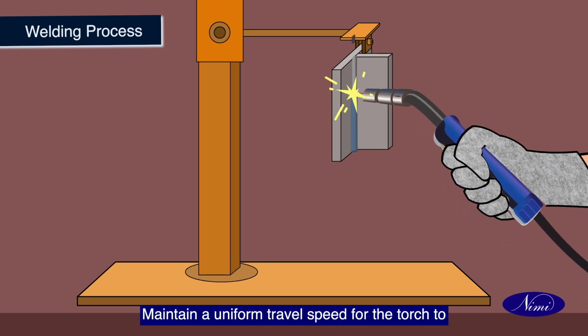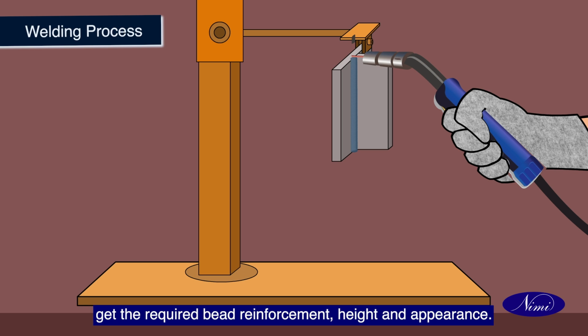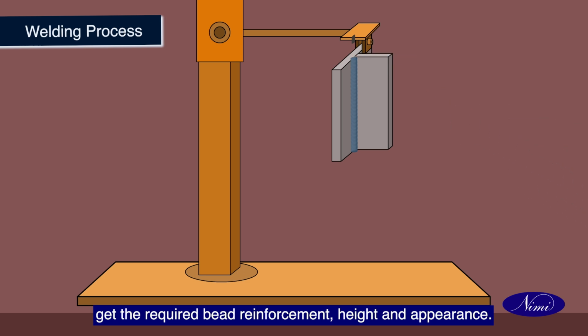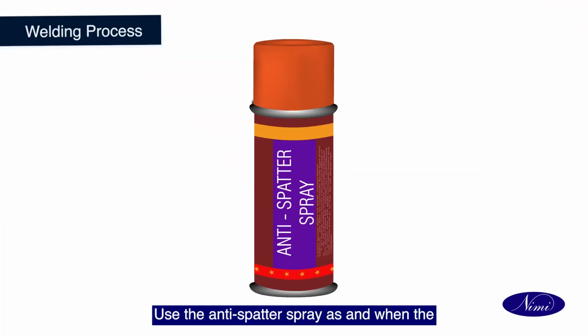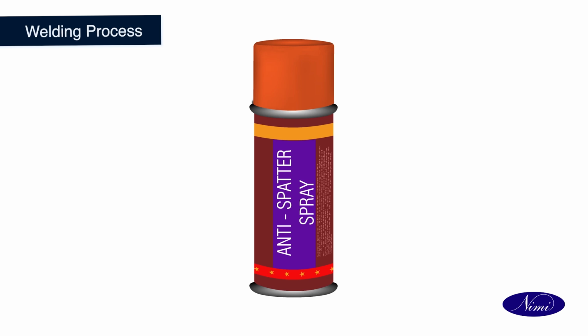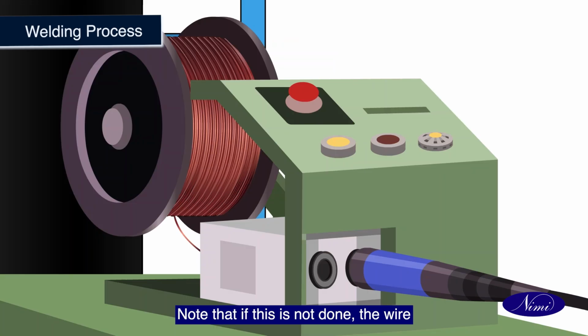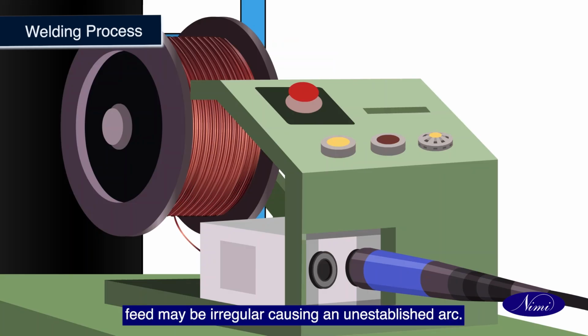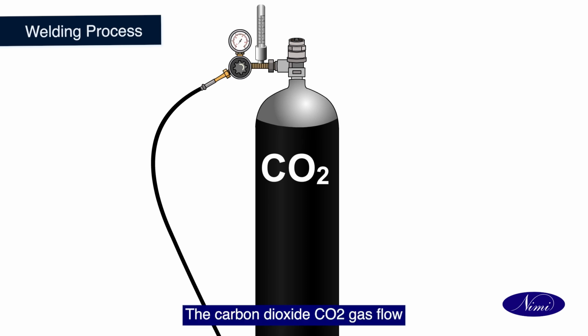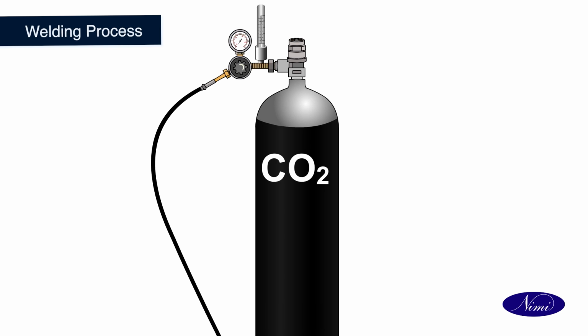Maintain a uniform travel speed for the torch to get the required bead reinforcement, height and appearance. Use the anti-spatter spray as and when the torch nozzle gets clogged with weld spatters. Note that if this is not done, the wire feed may be irregular, causing an unestablished arc. The carbon dioxide CO2 gas flow will not be uniform, causing atmospheric contamination of the weld and porosity.